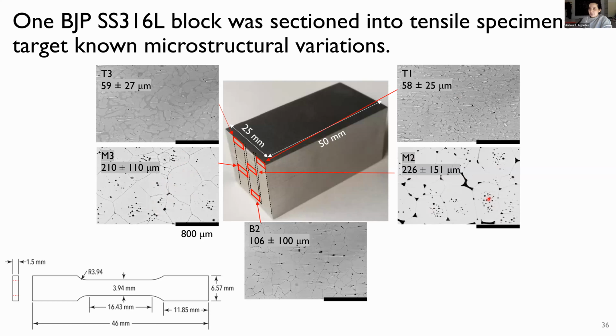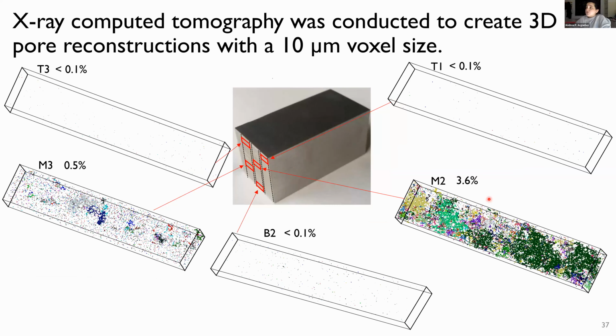And then some where you had this much more irregularly shaped pores, mostly concentrated between the grains, and we wanted to see the response of these and how those varied. So we started by doing X-ray computed tomography in each of those blocks. And what you see right here is that the pores that were showing up as irregular in that 2D plane were actually very large interconnected pore networks.